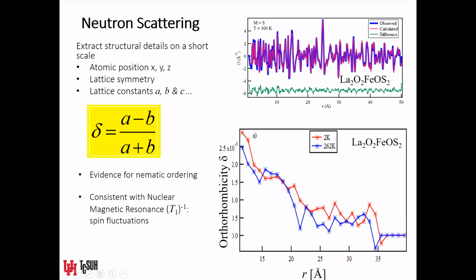So we applied neutron pair distribution function analysis to our Mott insulators. And with that, you can get numerous details. I said PDF, or pair distribution function, can give you atomic distances. It can also tell you about lattice symmetry and lattice constants, of course.